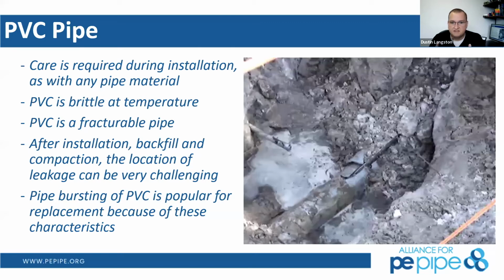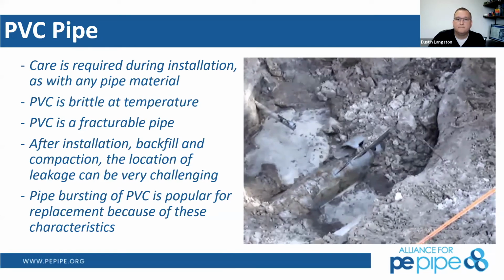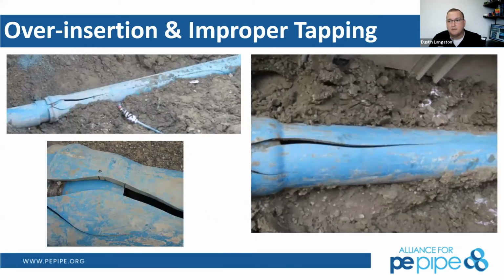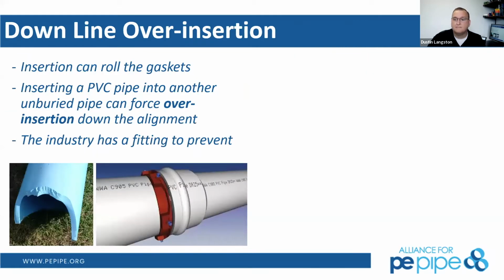So during PVC installation, care is of utmost importance. It's especially important to restrain those joints, usually by burying the pipe as you go. If you don't do this, you can actually get a forward over insertion of where you had already been. You already stabbed it to the correct depth, and now we're going to go down line and stab the next joint. If it's not restrained ahead of time, you're going to over insert down line, and that's what this actually looks like right here.